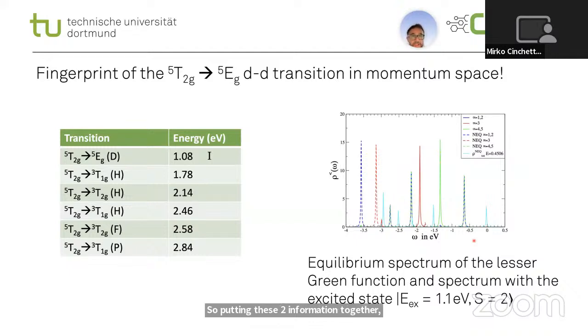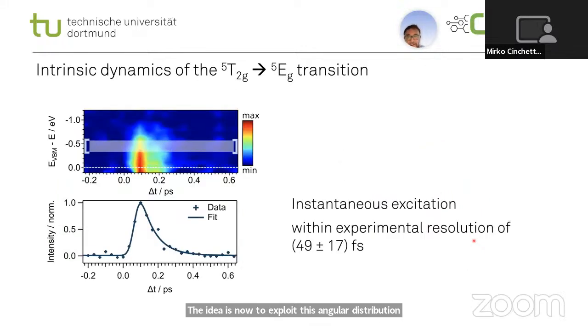So putting these two pieces of information together, our interpretation is that indeed, in our time-resolved experiments, we can see a fingerprint of the localized transition in our transient signal. Of course, there are still a lot of things that we need to understand. Since we have these very nice momentum maps, the idea is now to exploit this angular distribution to learn even more about these excitations. But we can already do something.